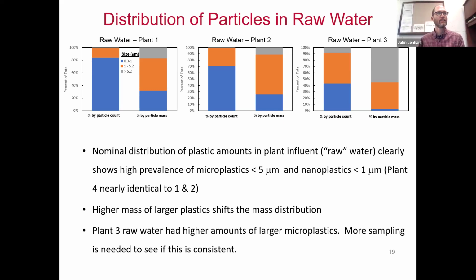So you can see when you look at concentration based upon the particle count, it skews towards the nanoplastics. There are a lot of very small particles in this case. And when you look at it in terms of the mass, the larger mass associated with the fewer, bigger particles changes the distribution of the particles. That's why the color shifts, because the larger microplastics, with their larger mass, change the proportion of the overall plastic distribution.